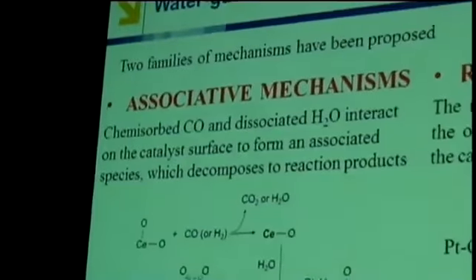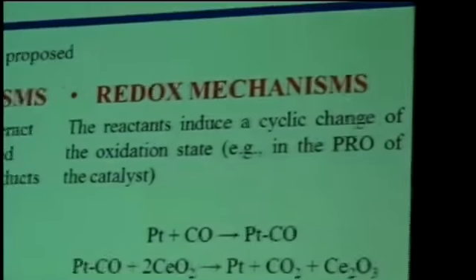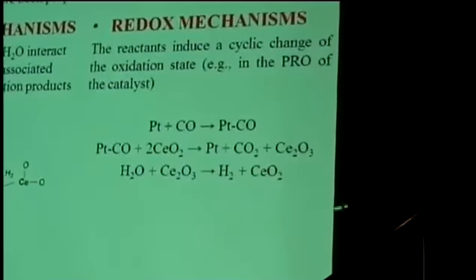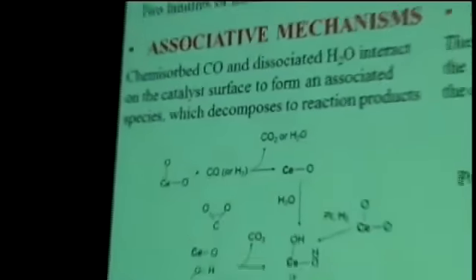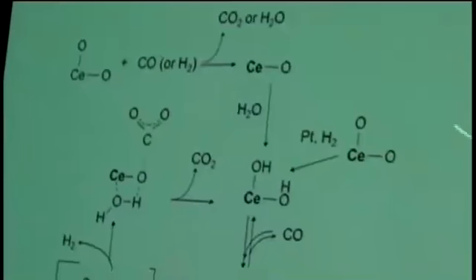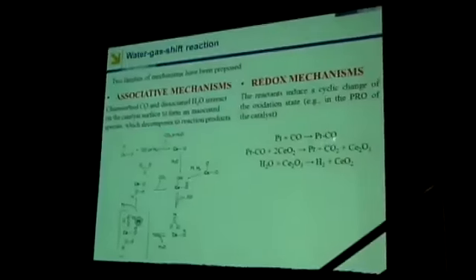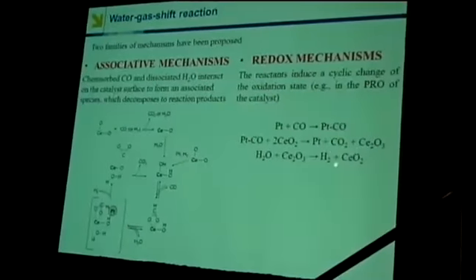So to understand how the dopants work, we first need to look at the families of mechanisms that have been proposed for water gas shift on these kinds of catalysts that rely on the synergy between the metal and the partially reducible oxide. And so on the right we have the redox mechanism family. And I show an example here where CO is adsorbed on platinum, reacts with the ceria, and reduces the ceria. Really it's removing an oxygen atom from the surface, and then water reoxidizes the ceria and liberates hydrogen in the process. And so in this mechanism, the ceria is cycling through the +3 and +4 oxidation states at the surface.